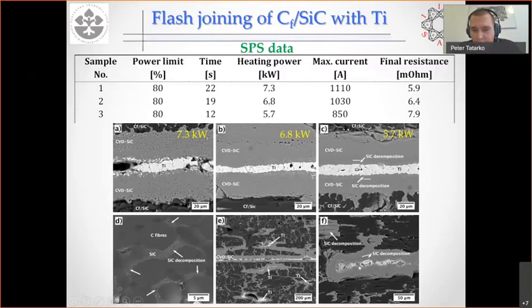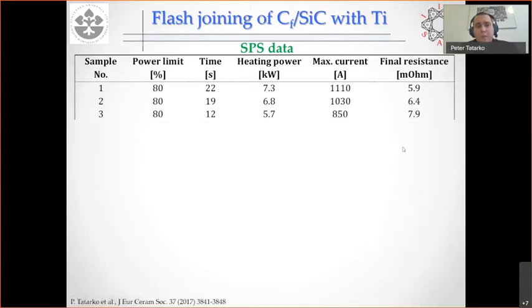Another issue we had that you can see here is titanium. Here is the joining interface, but we found titanium even at places far away from the interface. So basically the titanium melted, and because these materials are porous, it went everywhere. So it was really not a successful result, but we could see a clear effect of the power. So that's what we did then.